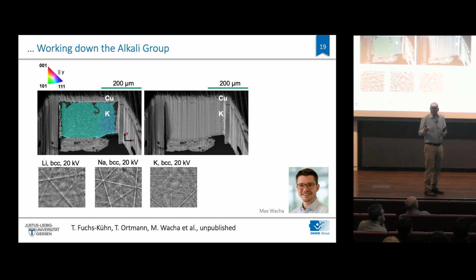Now, sodium has a lower melting point and has a higher diffusivity, so that's why you can more easily grow thicker sodium films. That makes sodium, of course, quite interesting. This is needed because 1 milliamp hour per square centimeter charge in the case of sodium makes roughly 10 micron length change, where it's only 5 micron for lithium.